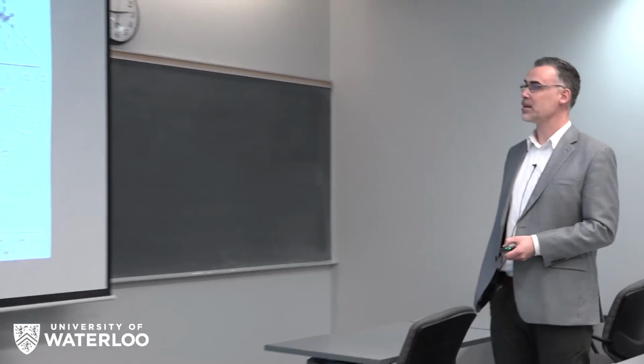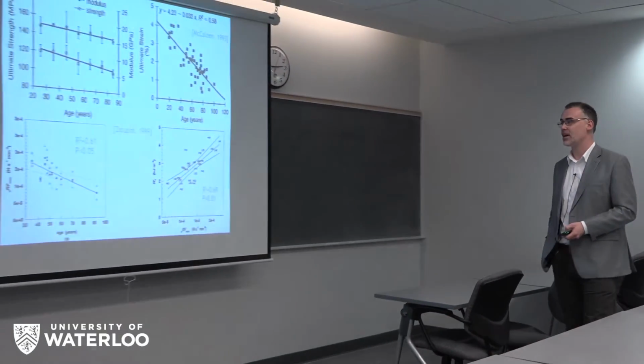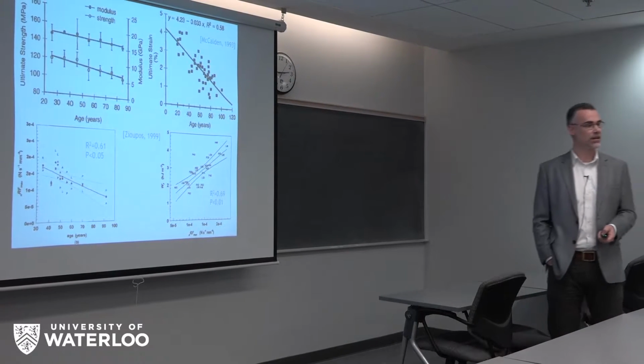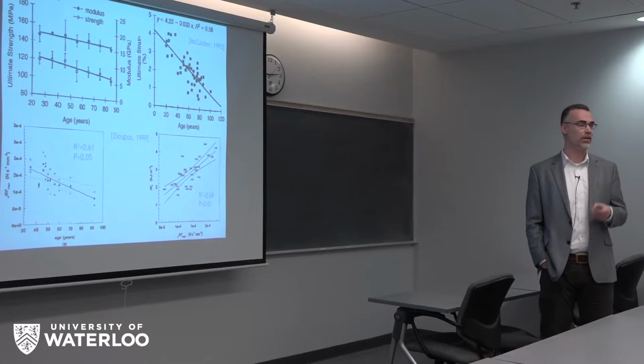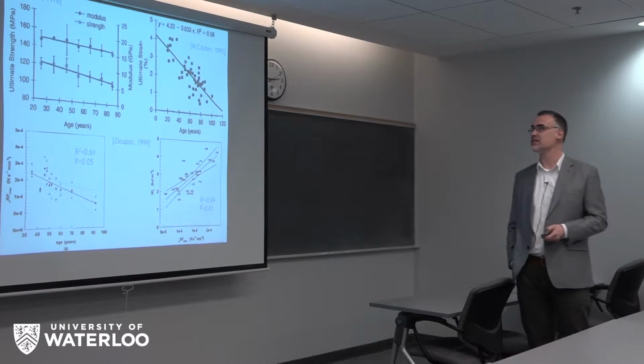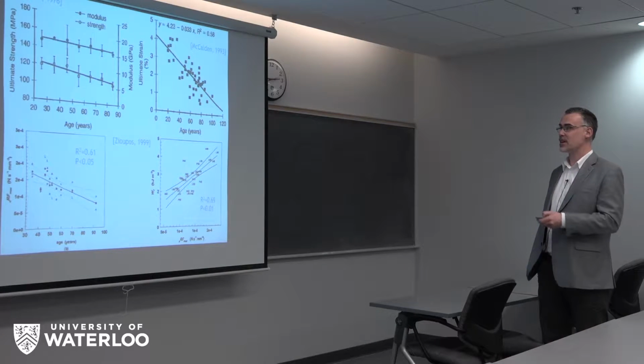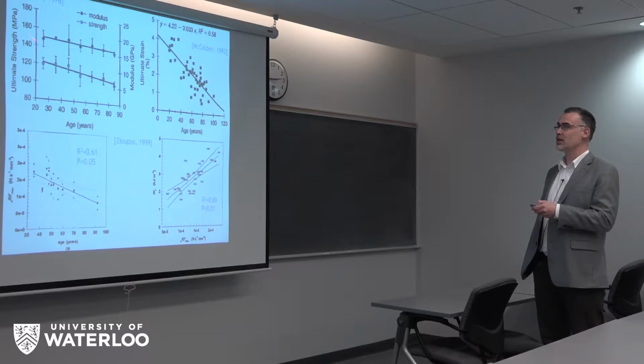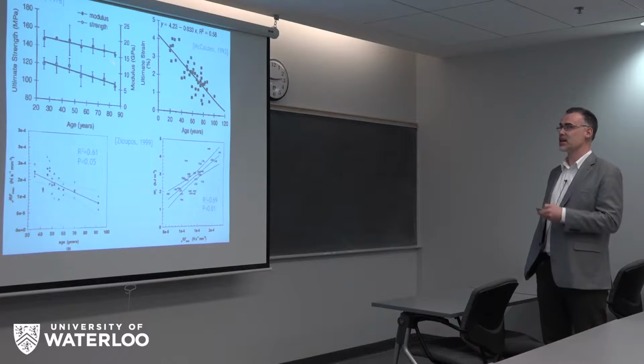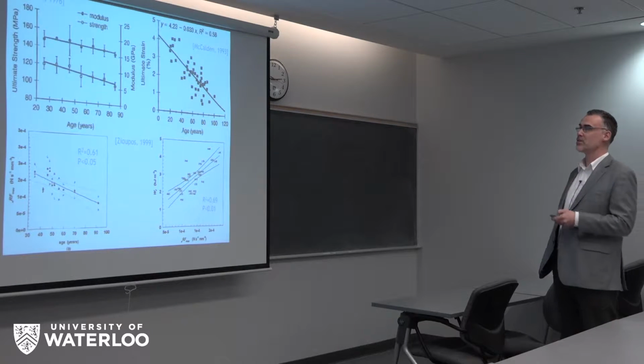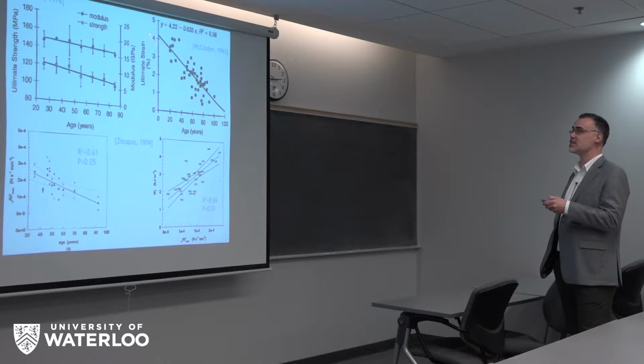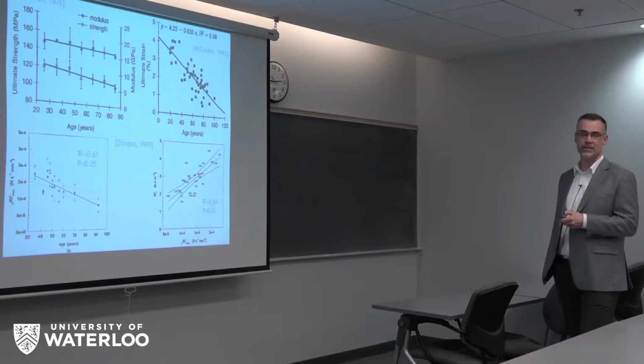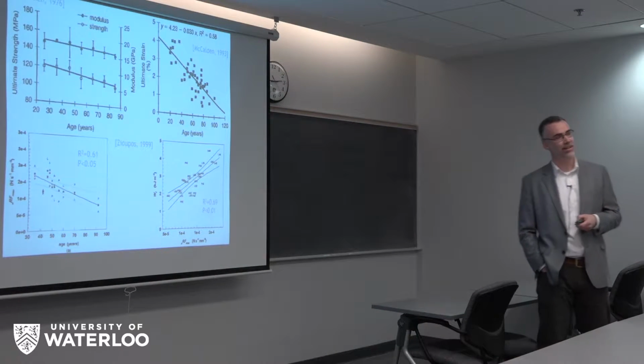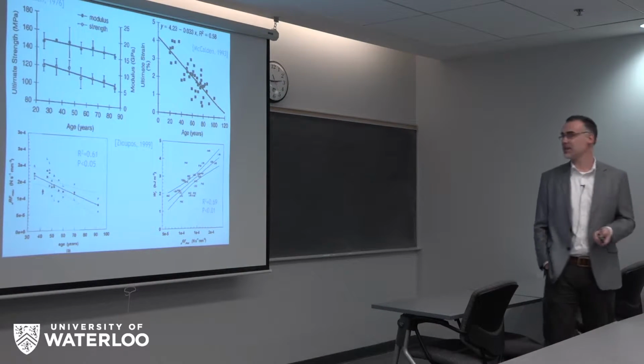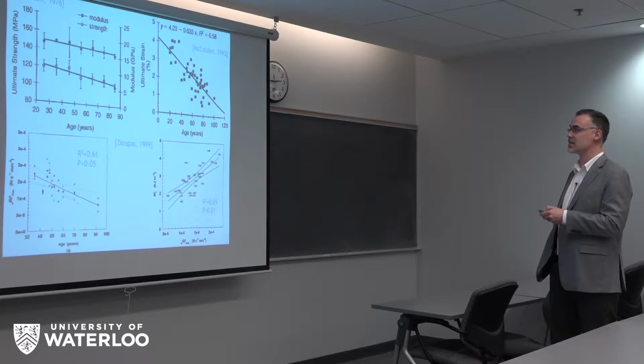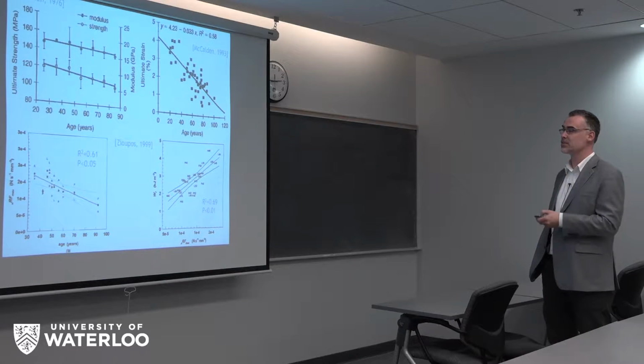But at the time, I'd been reading a lot about the effects of aging and disease on collagen in bone and what it does to the mechanical properties. And it turns out with age that ultimate strength and elastic modulus don't actually change that much. What actually changes a lot with age is the amount of strain that the bone can accommodate before fracturing. So this is a severe loss in ductility in a very strong relationship.